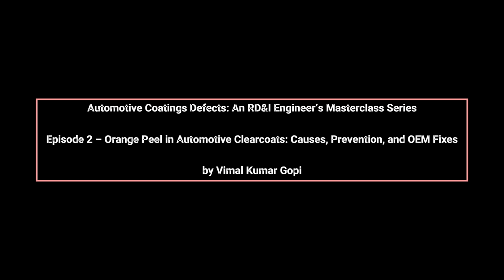Process parameters are equally critical. Spray equipment, atomization air pressure, nozzle selection, gun distance, and travel speed all influence droplet size, deposition uniformity, and wet film flow. Improper atomization may result in larger droplets that take longer to coalesce, reducing leveling efficiency.